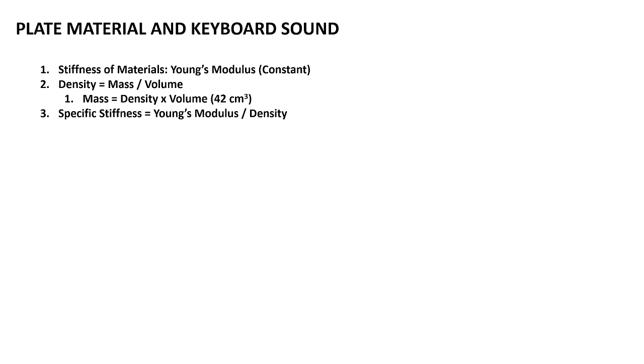Now there's this metric called the specific stiffness. It's a measurement of the stiffness versus the weight ratio. This is actually something very important in the aerospace industry because if you're building an airplane, you want materials that are very stiff and also very light. So if the specific stiffness is high, it means that it's a very stiff material with a very low weight. It's calculated by taking the Young's modulus and then dividing it by its density.